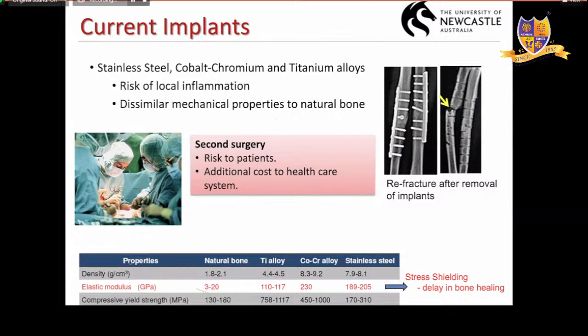And in addition, there are some dissimilar mechanical properties to the natural bone. If you look at this table here, the properties of these so-called conventional alloys, titanium, chromium, cobalt, and stainless steel, are quite different from natural bone. Especially focus on the elastic modulus, it's quite high. When there is a mismatch in those mechanical properties, this leads to an effect called stress shielding. Stress shielding will delay bone healing. It doesn't heal naturally, so it is quite undesirable.